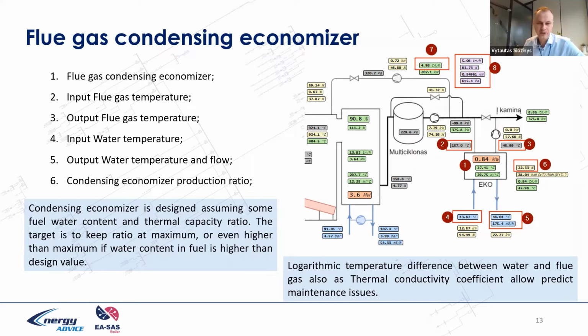in the flue gas condensing economizer. Additionally, we calculate the logarithmic temperature difference between water and flue gas, and the thermal conductivity coefficient, which allow us to predict the condition of the economizer, and this prediction allows us to understand where cleaning should be performed. Additionally, a pH meter is installed here, and we can also calculate the dew point temperature. Why is the dew point interesting? We should understand how far the flue gas output temperature is from the dew point temperature. It's like a gap between the capability to condense water from the flue gas and the real condensing situation.